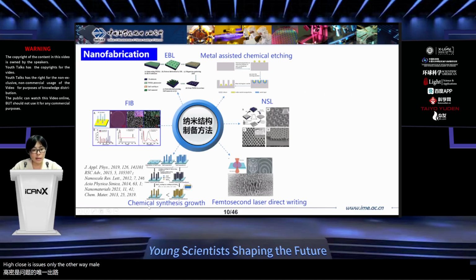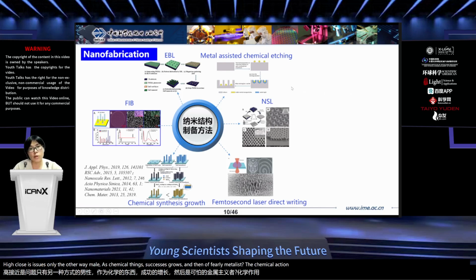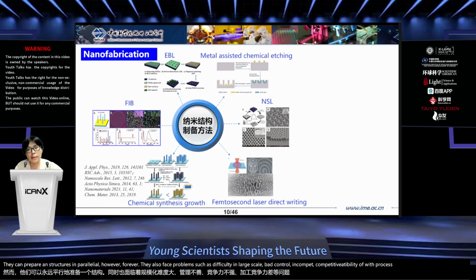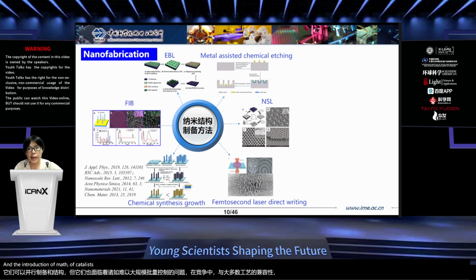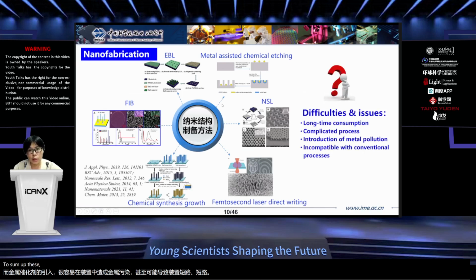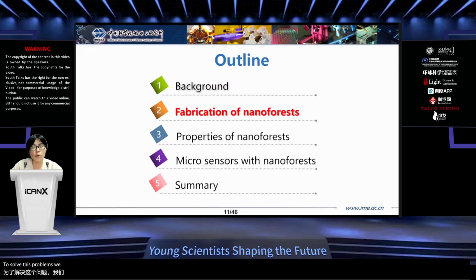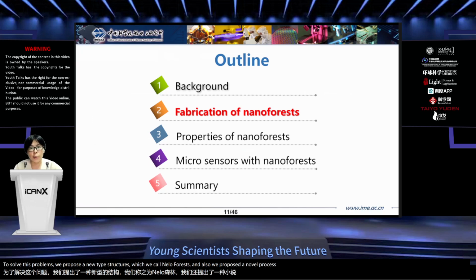On the other hand, chemical synthesis growth, nanosphere lithography, and metal-assisted chemical etching technologies can prepare nanostructures in parallel. However, they also face problems such as difficulty in large-scale batch control, incompatibility with CMOS processes, and the introduction of metal catalysts that may easily cause metal pollution in the device, which may even lead to short circuit of the devices. To sum up, these are the challenges of the current preparation processes. To solve these problems, we propose a new type of nanostructures, which we call nanoforests. And we also proposed a novel process to fabricate the nanoforests.